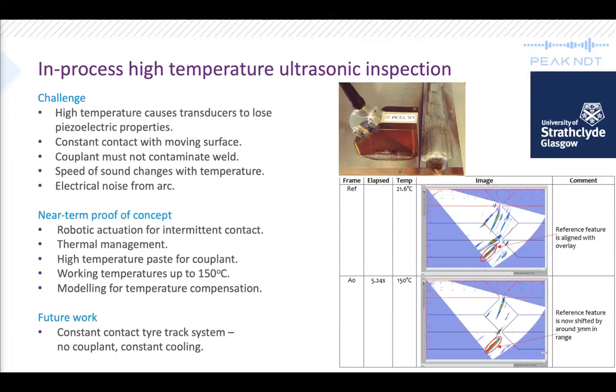So it was initially lower TRL technology at the beginning of this program, but the rate of development has been very impressive. And this is providing us in-process volumetric inspection of not necessarily the weld, but a recently deposited weld. So the challenges for in-process UT are quite considerable. Traditional piezoelectric transducers stop working above a certain temperature threshold, and your welding and preheat temperatures are significantly higher, so you have to have cooling and heat management considerations. The ultrasonic couplant that you use to interface between the material and the probe to transfer the ultrasonic impulse, the majority of those will either boil away at the preheat temperatures you're using or have the potential to contaminate and run into the weld and cause their own defects.